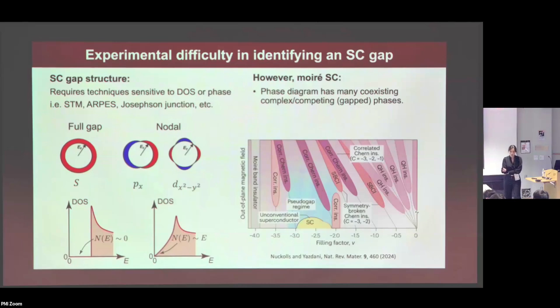However, there's a little bit of a problem in Moiré superconductivity. First of all, the energy scale that we're dealing with is very small. All these correlated phases are mostly milli-electron volt, and the superconducting gap might be even smaller than 1 milli-electron volt. And even within such a small energy scale, there are so many different phases coexisting in this phase diagram. You have superconductivity, correlated insulators, potential pseudo gap, and so many things going on, symmetry breaking, okay?